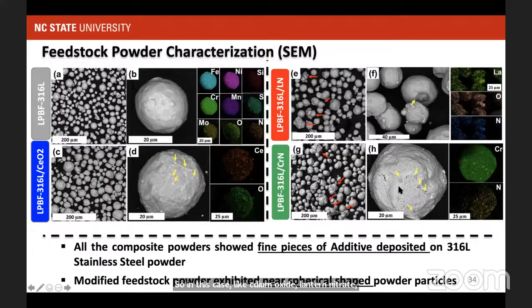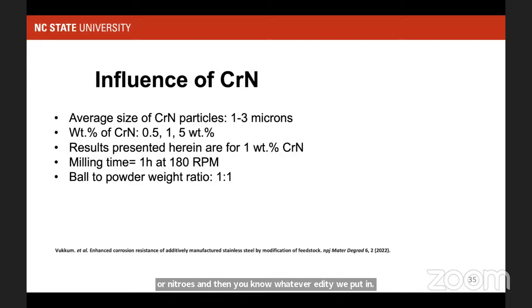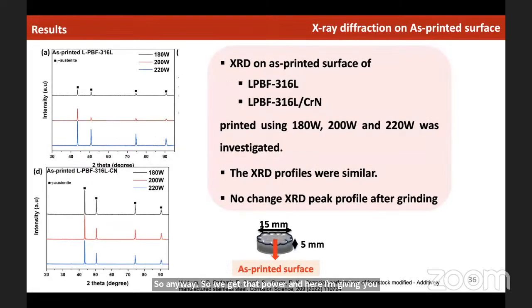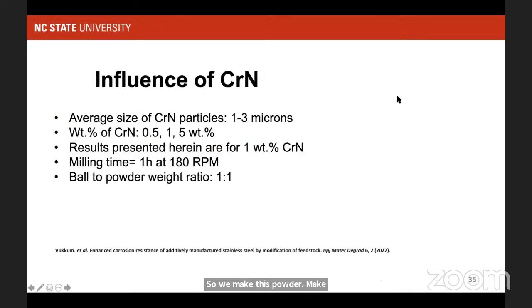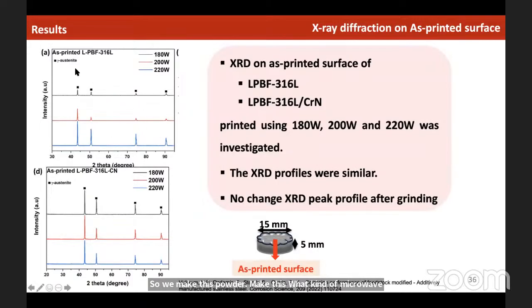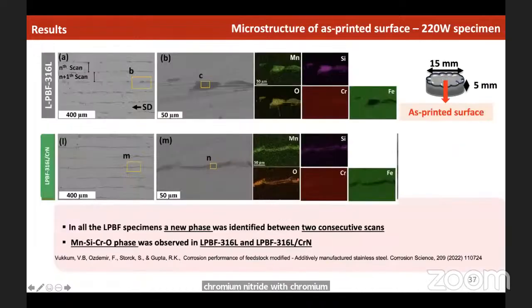If you look at those individual powders in the EDX analysis, you see that you coated those particles with the chromium or nitrogen, whatever additive we put in. So we get that powder, and here I'm giving you just one quick example for chromium nitride. We make those chromium nitride modified powders and use that for the 3D printing. And if I compare my as printed material without chromium nitride and with chromium nitride by XRD, we get similar data.